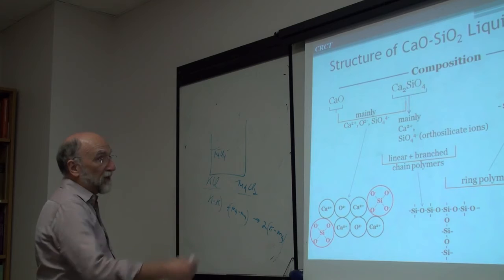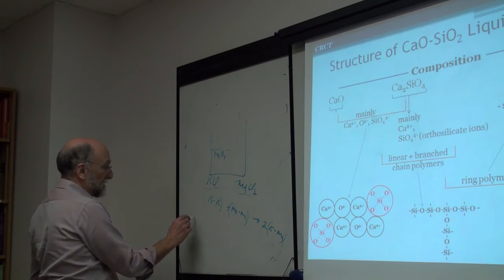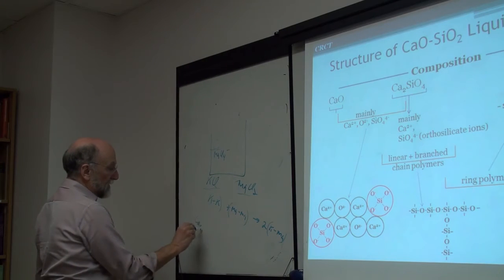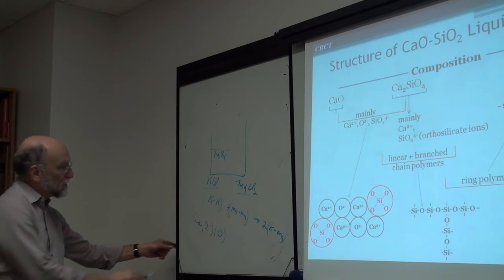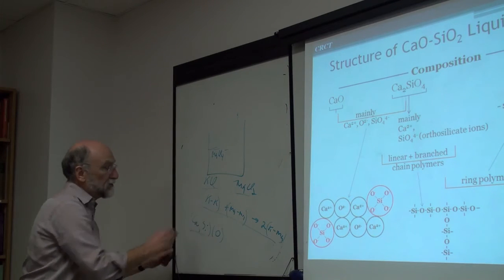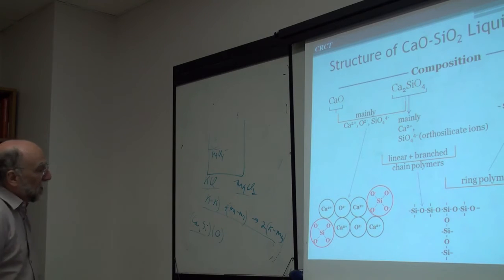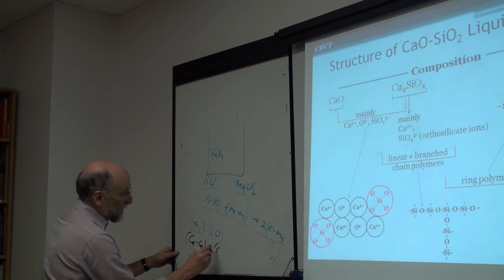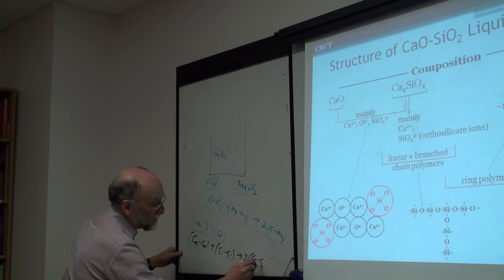Okay, so we're then treating the calcium silica system as calcium, silicon, oxygen. We treat it as a one sublattice model, exactly the same as this, a one sublattice quasi-chemical model. But we have a very strong tendency for calcium-calcium plus silicon-silicon to form 2 calcium-silicon.